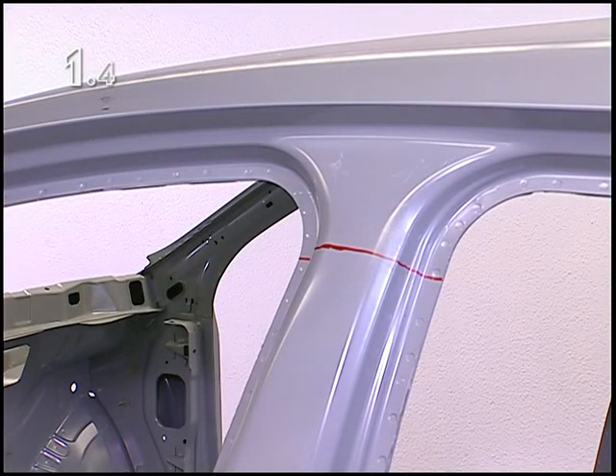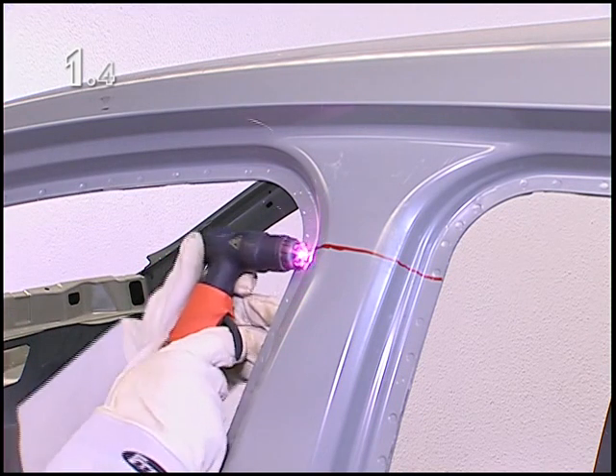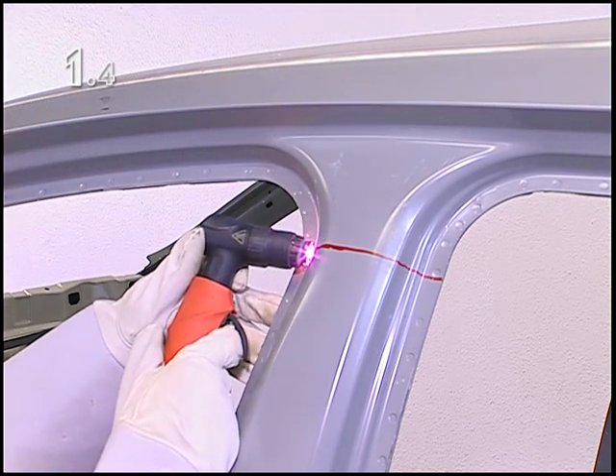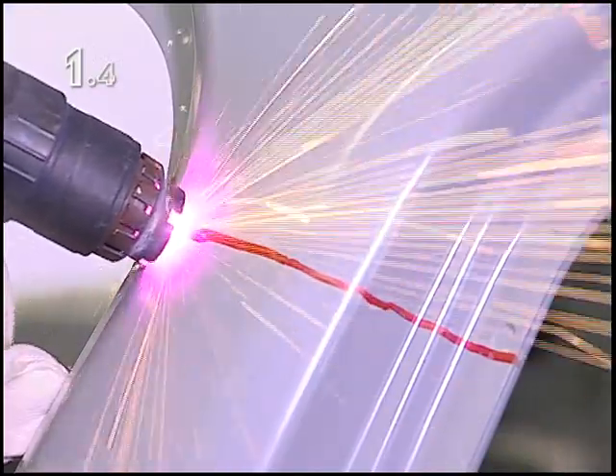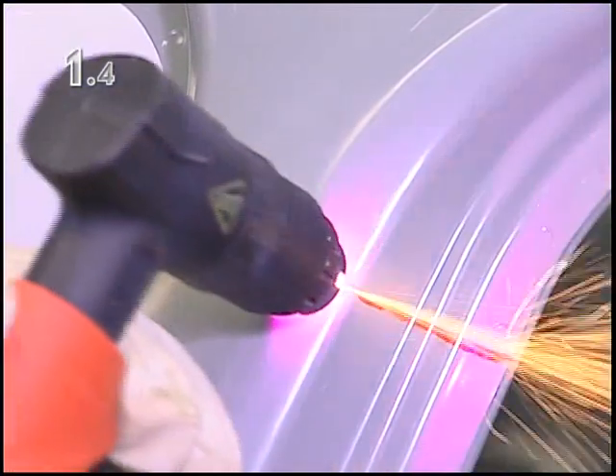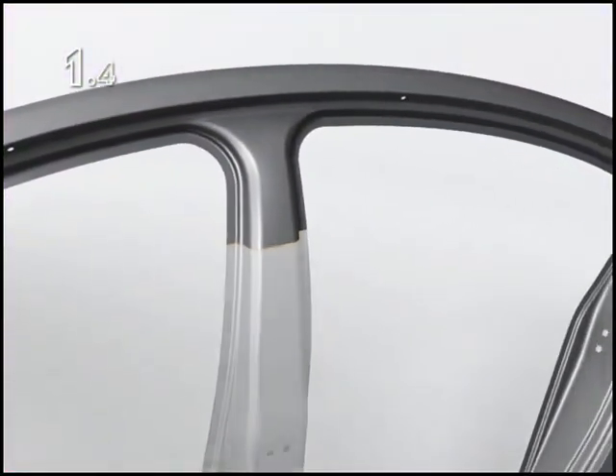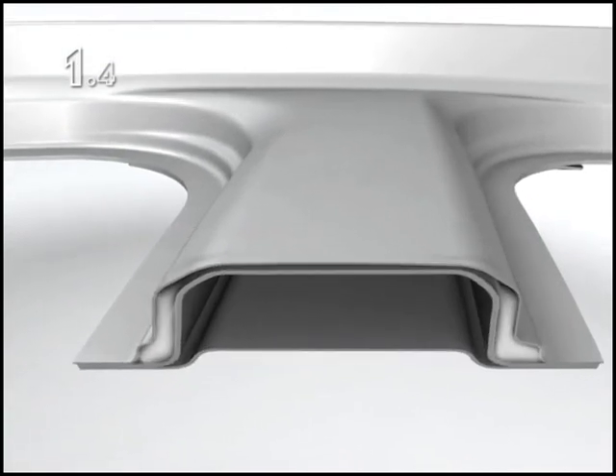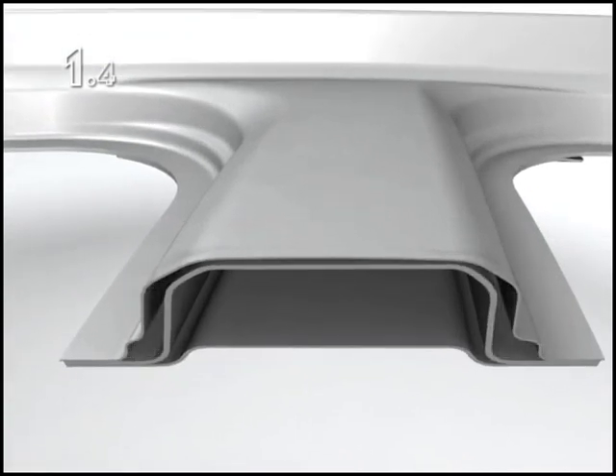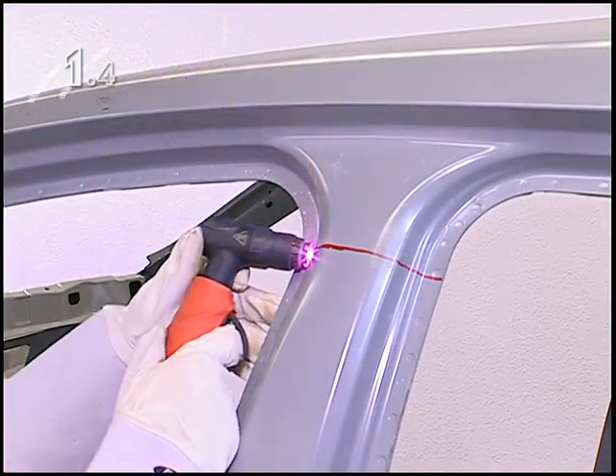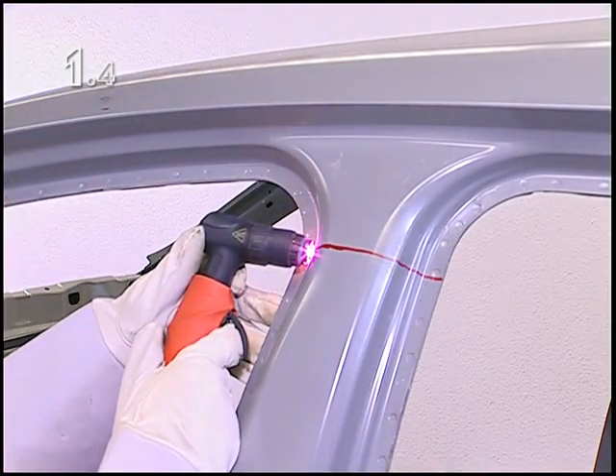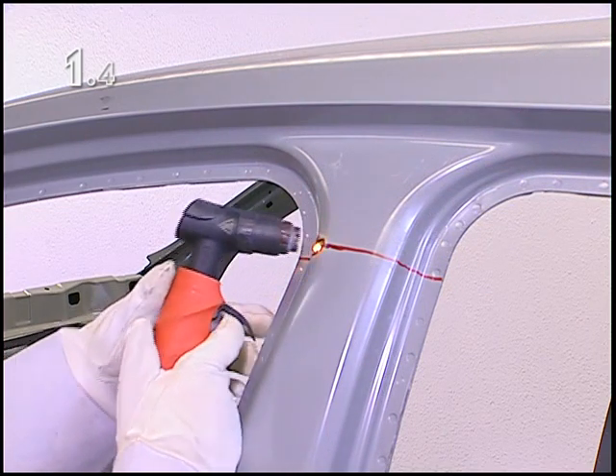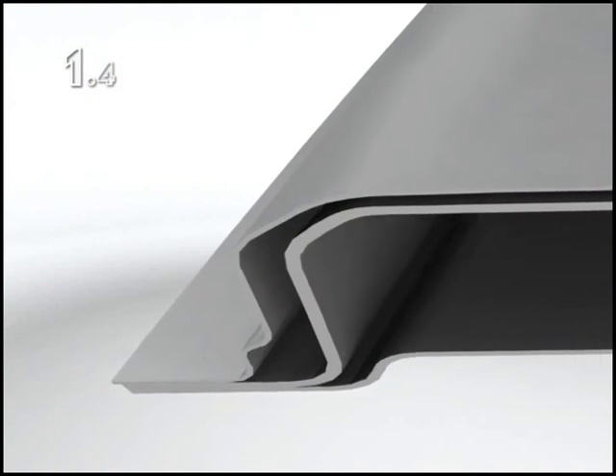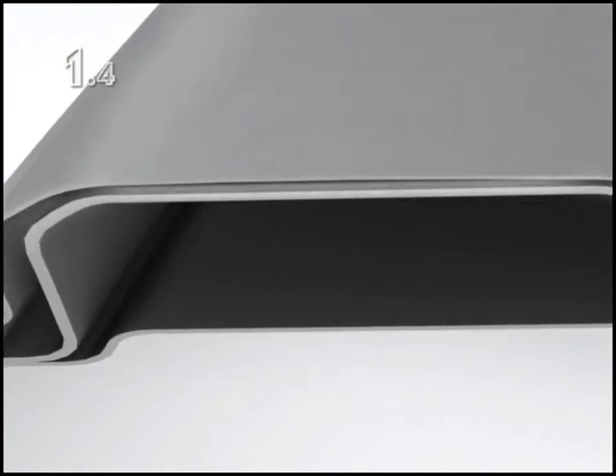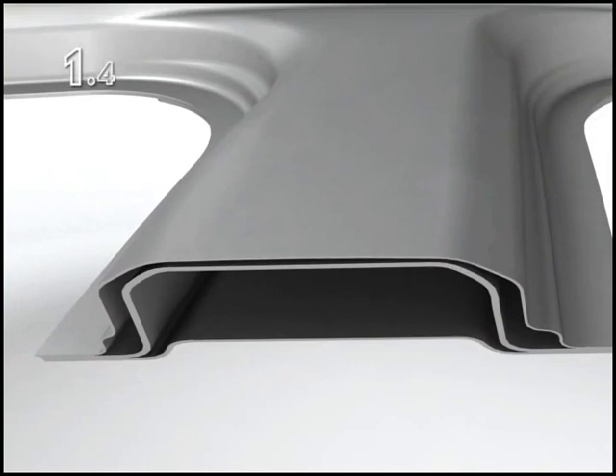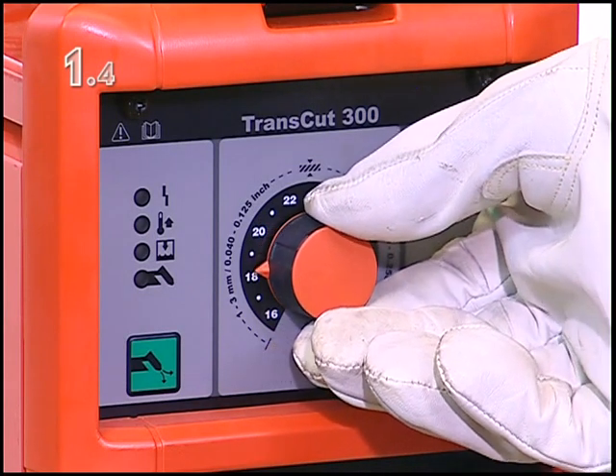When cutting out exterior panels, the reinforcements behind must not be damaged, just as with conventional cutting processes. The specifications in the service literature must be strictly adhered to. If there is a space between the exterior panel and reinforcement, it's possible to use the normal plasma cutting current setting and cutting speed. In order to cut at locations where the exterior panel is very close to the reinforcement, the cutting current must be reduced to avoid causing damage.